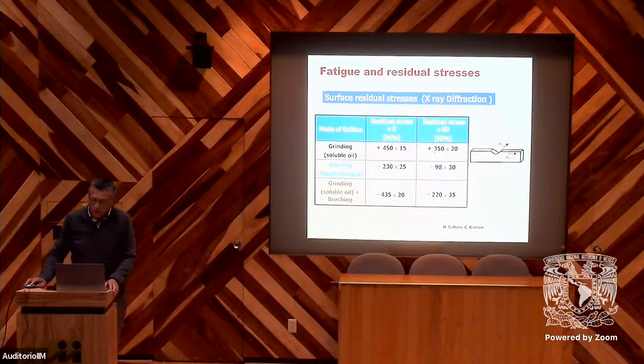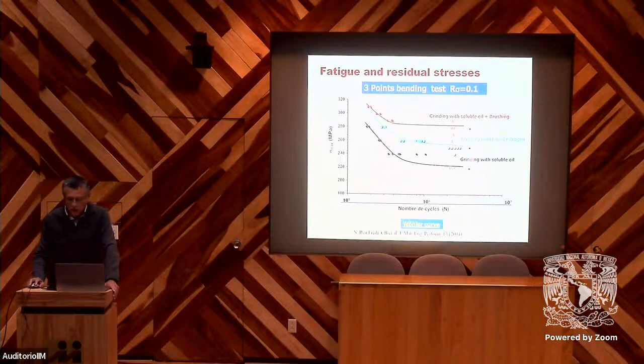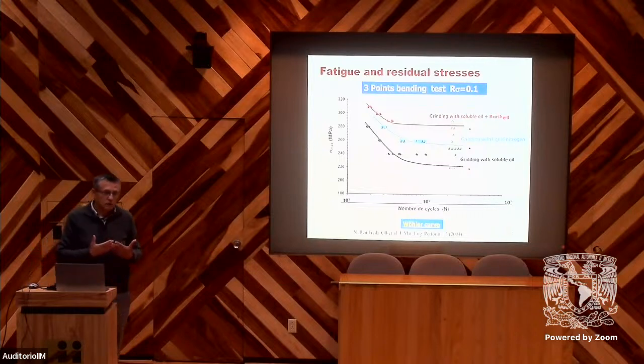We have here the value of the tensile residual stress for grinding in the classical conditions using soluble oil cooling. And now, if we reduce the thermal effect, that means we reduce tensile residual stresses. Using liquid nitrogen, we have better cooling, and then we can see that we reduce the value of these tensile stresses. And now, if we apply brushing after classical grinding, we can see that we induce a compression of the surface. So now we can compare the behavior in fatigue. Our initial state is grinding with classical cooling conditions, and with liquid nitrogen we have an improvement, and the best results are obtained using brushing after grinding. So we can see directly here the effect of residual stresses on the fatigue life.